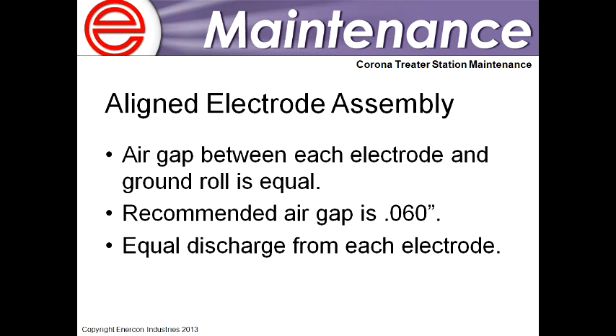And the other thing too is it's a balancing act. I'm not looking for precision necessarily. There's no tolerance per se. It doesn't matter if it's 52 thousandths or 60 thousandths. But really what we're looking for is whatever the electrode gap is set to. Again, our recommendation is 60 thousandths, to try and make it as consistent as possible on all of the electrodes.